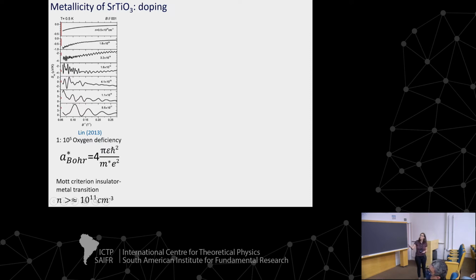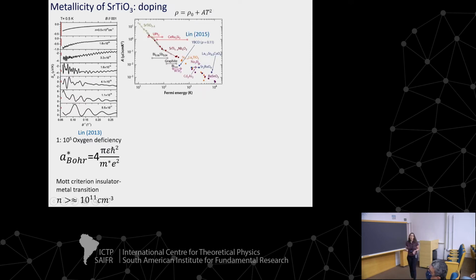So as it depends on the epsilon, we can reach the insulator-metal transition earlier than for other materials. Okay, if we look at some studies about the power law dependence of the resistivity, we can see that the T-squared behavior is observed, and the A coefficient is quite high. Actually, it's comparable with some heavy fermions.